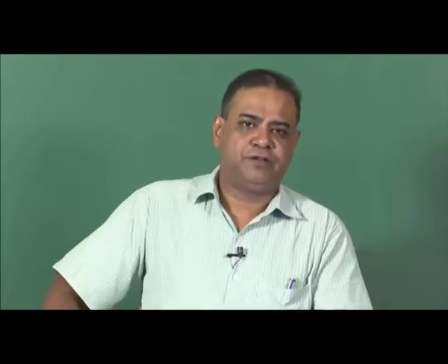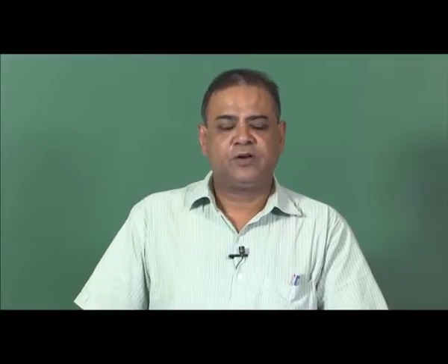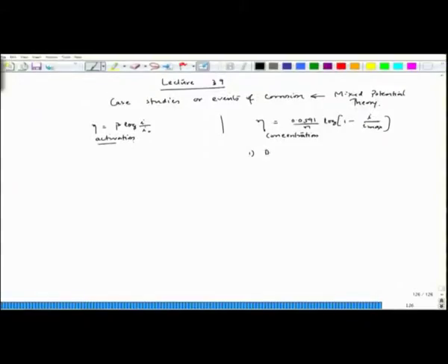There are 2 possible reasons. One is, of course, that when you consider anodic polarization, there should be depletion of metal ions at the interface due to the corrosion event, but since it is anodic polarization, metal is going into ion form. So there would be enough supply of metal for the formation of metal ions. So the depletion of metal ion is unlikely.